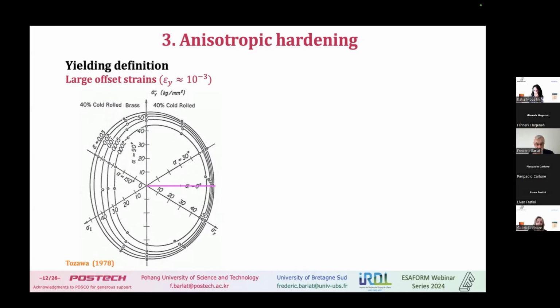So we see that we have some distortion of the yield surface, in particular some kind of flattening in the direction opposite to the former loading restraint. And if we increase the strain, then we see that we tend to recover a more regular shape.